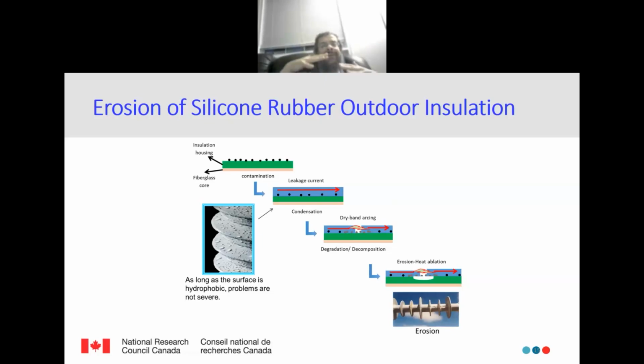Now, once you start to have a leakage current on the surface, certain parts will have higher current density than others, so you will start to have dry bands. These dry bands will have very high electrical stress on them, which will lead to what we call dry band arcing on the surface, and this dry band arcing will lead to the erosion of the material. Next, please.